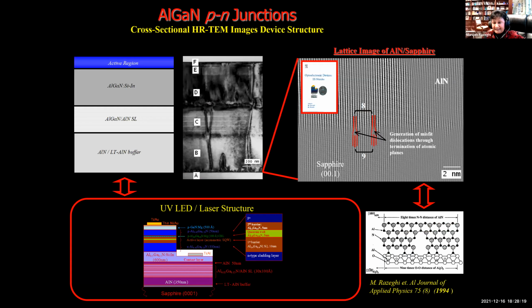But one of the important things, look here, is that material growth is so important for anything, and especially for aluminum nitride and gallium nitride, we do not have any substrate. Despite 50 years of everybody working, nobody can make a substrate of gallium nitride or aluminum nitride. So we use sapphire, because sapphire has a similar symmetry to gallium nitride. If you look here at the growth of aluminum nitride on sapphire, every 9 planes of sapphire are equivalent to 8 of aluminum nitride.